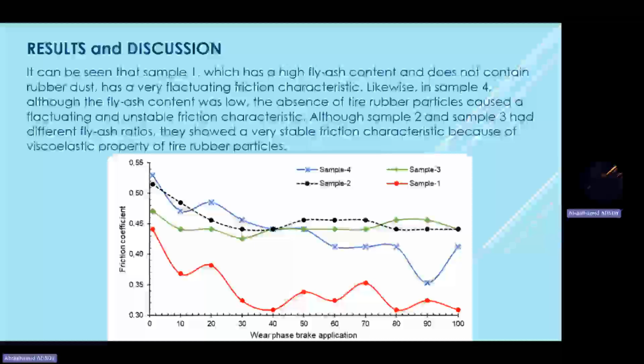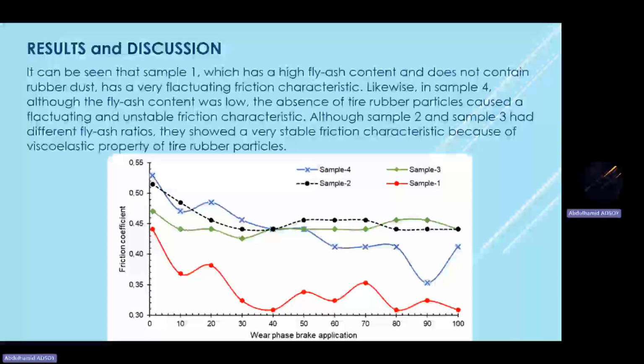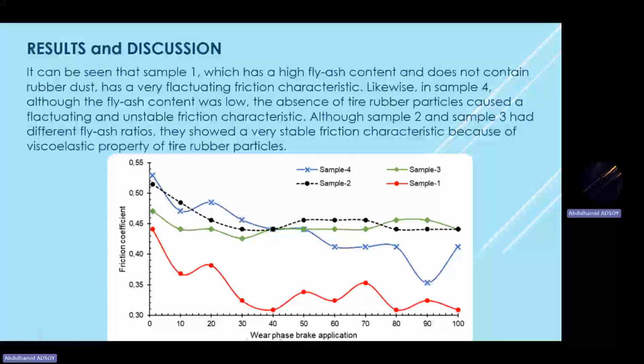Now, from this graph, we can see that the friction coefficient fluctuations are visible for sample 1 and sample 4, while samples 2 and 3, which include tire rubbers, fluctuate more steadily. Now, with the low fly ash content in sample 4, we can see that samples 4 and 1 fluctuate very rapidly by the brake applications in the wear phase.